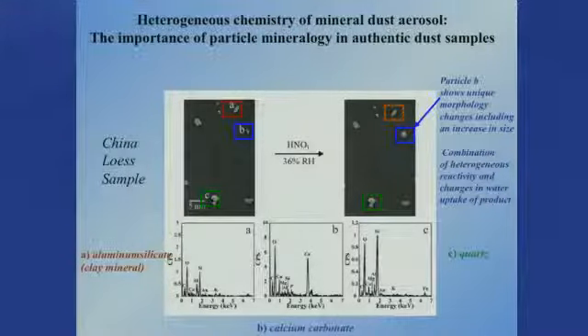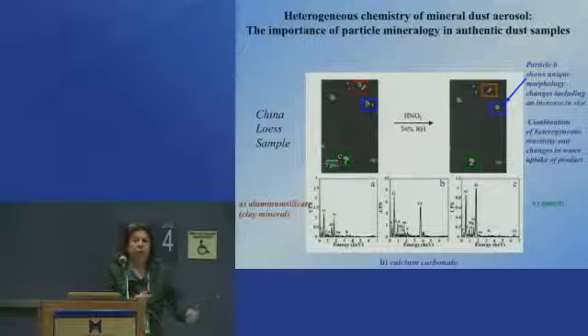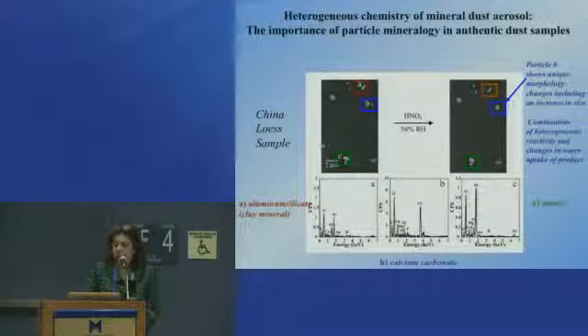And then here we're looking at the heterogeneous chemistry of mineral dust. We're looking at a more complex system. This is a China loess sample. Here I've highlighted 3 particles, A, B, and C. A is an aluminum silicate, B is calcium carbonate, and C is a quartz particle. And again, with reaction with nitric acid, we only see that particle B has undergone morphology changes. And again, in this complex mixture, what we saw with some of the single components, we can explain readily from the chemistry I just mentioned a moment ago.